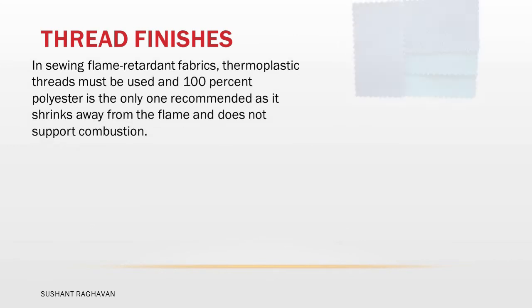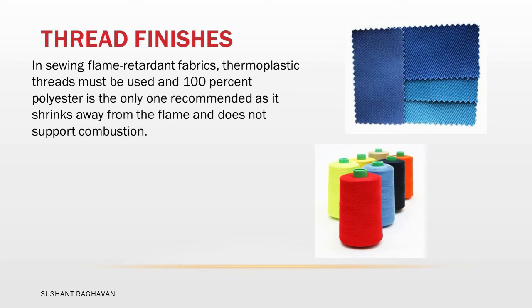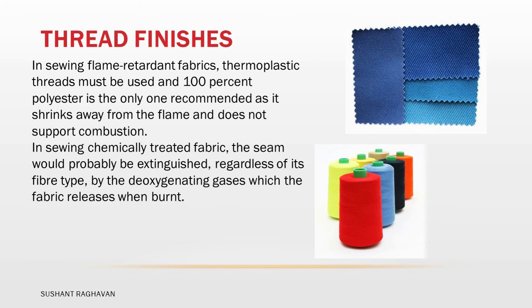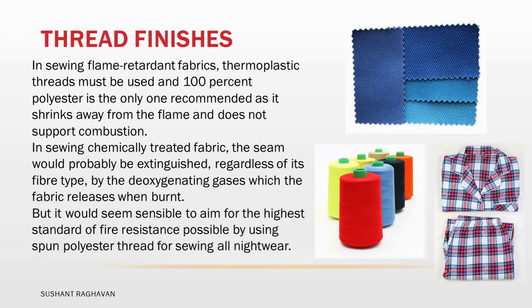In sewing flame retardant fabrics, thermoplastic thread must be used and 100% polyester is the only one recommended, as it shrinks away from the flame and does not support combustion. In sewing chemically treated fabric, the seam would probably be extinguished regardless of its fiber type by the deoxygenating gases which the fabric releases when burnt. But it would seem sensible to aim for the highest standard of fire resistance possible by using spun polyester thread for sewing all nightwear.